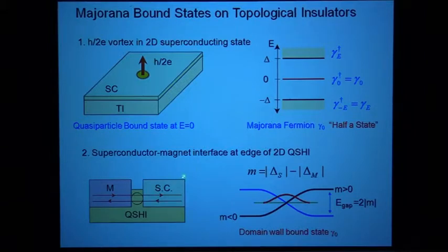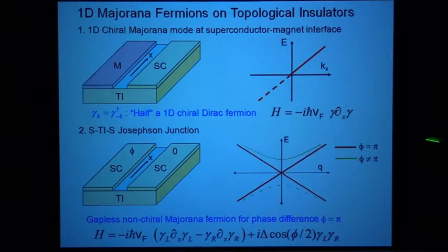There's a difference, though, which is in the one-dimensional topological superconductor, you actually have to break time reversal symmetry in order to get the Majorana mode, and the superconductor itself breaks time reversal. Here, the superconducting state doesn't break time reversal, but it's the insulator on the outside that does break time reversal. And so this is a complementary situation to the one-dimensional topological superconductor.